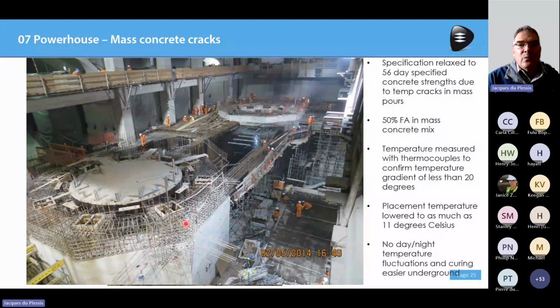So what we did was we relaxed the specification that specified 25 MPa at 28 days. We relaxed that to 25 MPa at 56 days. And that allowed the contractor to increase his fly ash content to 50%. The temperature was also monitored continuously while the concrete hydrated.